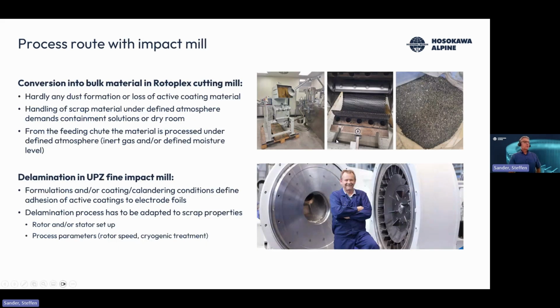These cutting mills we use, the Rotoplex, you can see the rotor here. They have a special rotor design that reduces dust formation and formation of impurities. And by changing the discharge grade here with different designs, you can adapt also the fragment size, and you can adapt your process to the needs of your product. But since this is something we've learned so far, every material, every scrap is a bit different, behaves a bit different, and needs some other process conditions in order to get a good yield with low impurities.